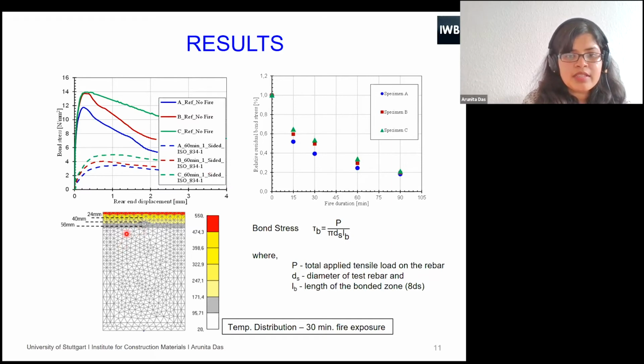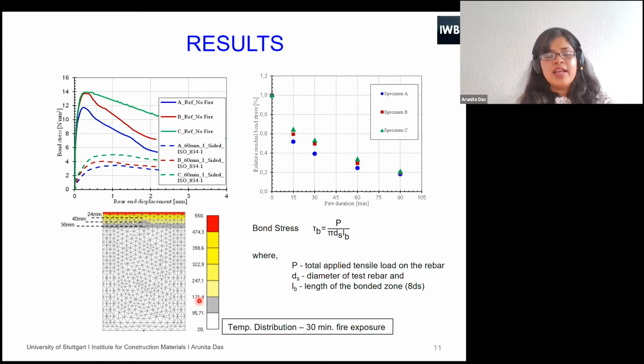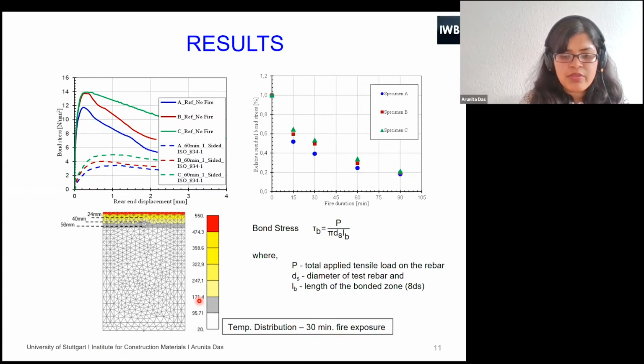Here is the temperature variation inside the layers of concrete. So basically you can see the top layer, when the top layer is around 550 degrees, the bond layer, I mean between concrete and steel, it's around 170 degrees. So there is a huge difference in the temperature gradient. This is what we wanted to capture.